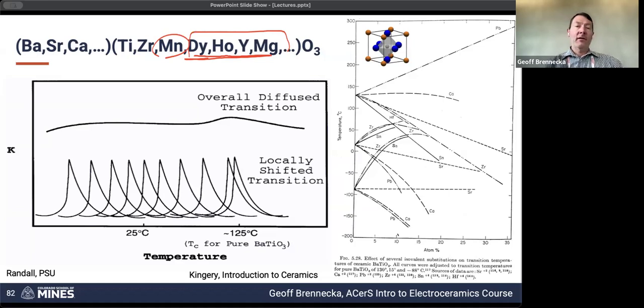For example, manganese. Manganese is considered a magic dopant by many people in the industry because it's got 7 different valence states, and it is perfectly happy compensating for whatever other defects happen to be around. So just sprinkle in a little bit of manganese and your resistivity will go up in barium titanate. It does wonders. The other fun thing about the different lanthanides is that they're all 3+ for the most part, but they have gradually changing ionic radii.